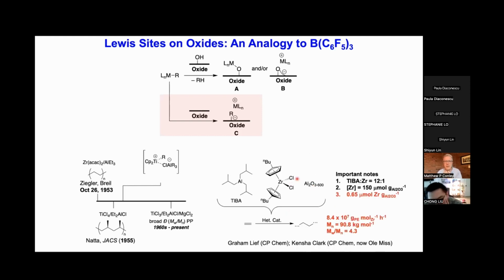So I put this in the context of a catalyst that we've studied in collaboration with Chevron Phillips. This is not a catalyst that they use commercially, but it is representative of a state-of-the-art heterogeneous catalyst for olefin polymerization, where you take a metallocene, an oxide, and an alkyl aluminum, and then you make the polymer. And these are very active catalysts, though I'm told by my minders at CP Chem these aren't that active.